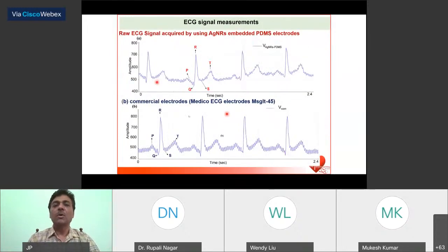Here I'm showing you a comparison of the signals we obtained. This is raw data, obtained without any image processing, from our electrode using this circuitry. From the noise point of view, what we found is that it is even much better than the conventional, commercial electrode.